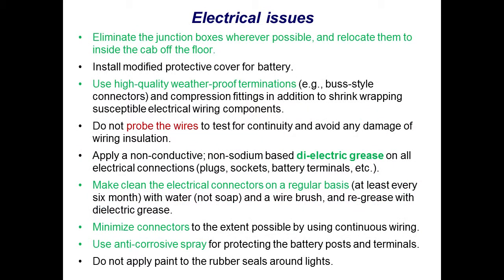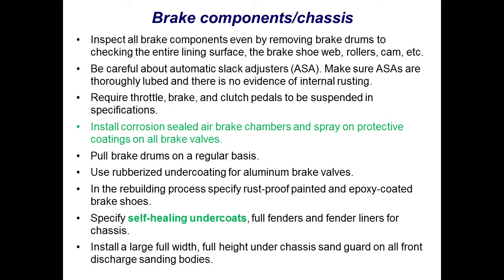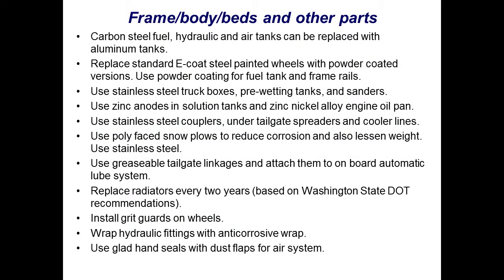Well, there are also electrical issues. There are practices you can do, so I didn't want to go too much there. Don't probe your wires again, otherwise you dent them and you get localized corrosion. And some grease can help you. Basically, you're preventing water and oxygen from accessing your metal. So many of these items are available in the reports on Clearwater's website, so I didn't want to go too much into that. In terms of chassis and brake, again, you could do protective coating, you can do spray-on corrosion inhibitors, making sure they're clean before you do that. And for other parts, the list basically is from the survey responses.